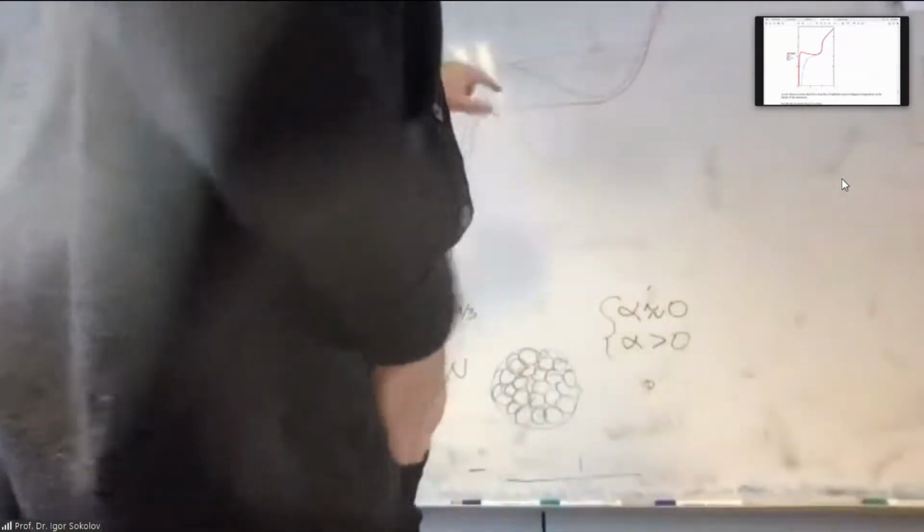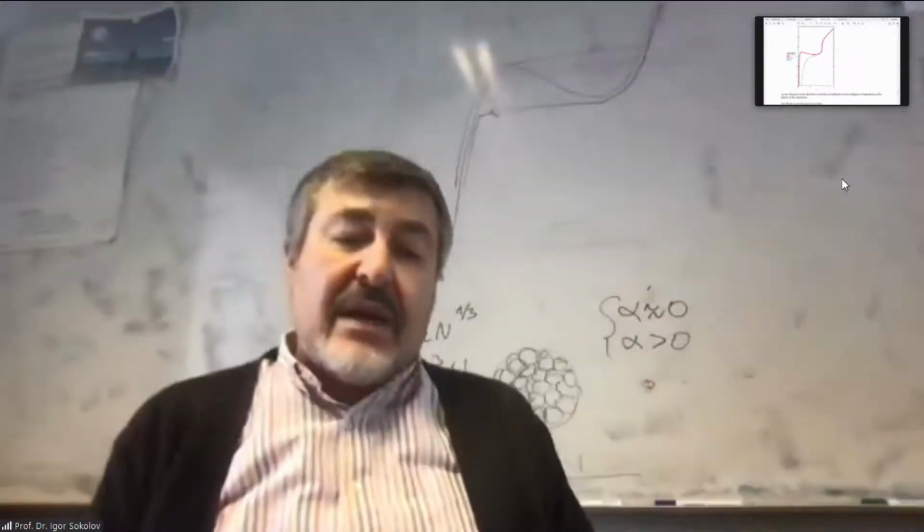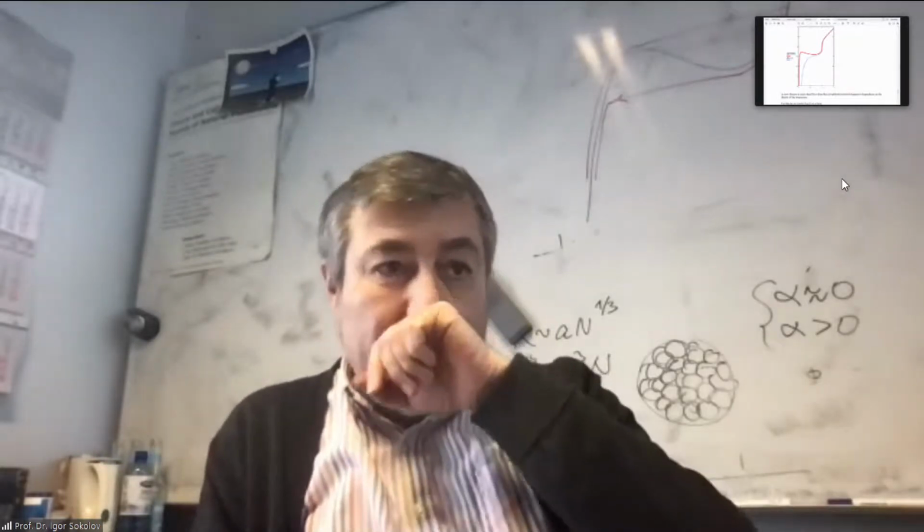And these immediate changes, this direct transition, is called the collapse of a polymer. And collapses are typical for high molecular weight polymers, but even more typical for stiff molecules, which I didn't show because we never built a variant of Flory-Huggins for stiff. It's not as simple.